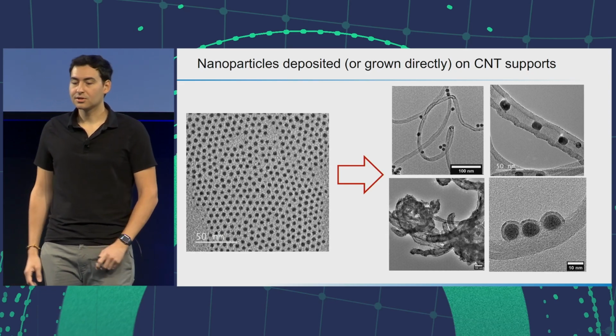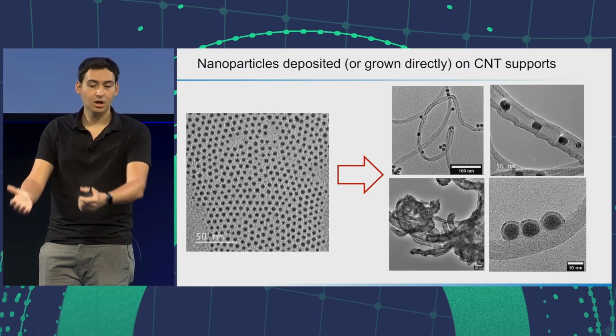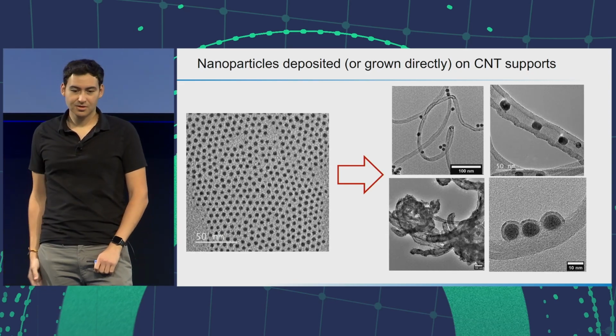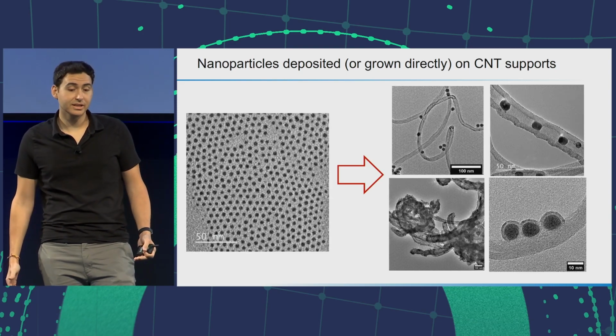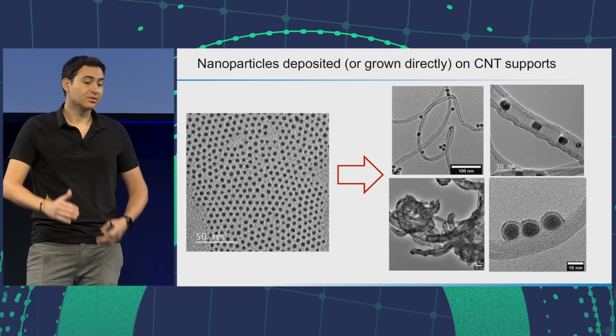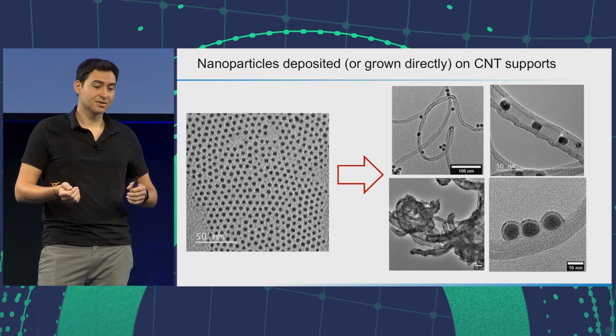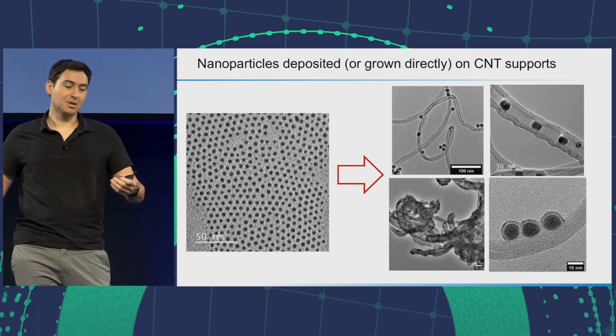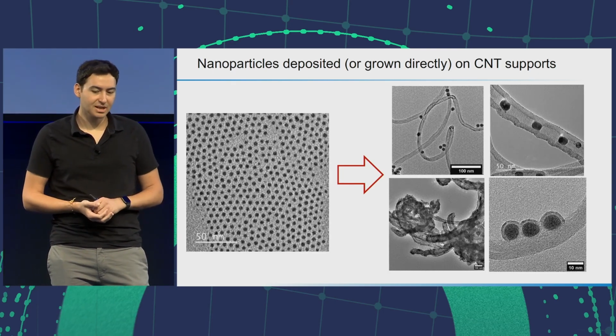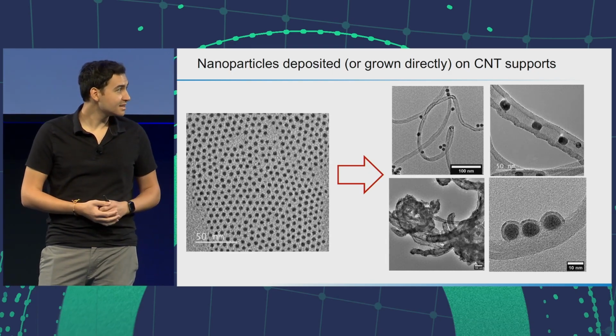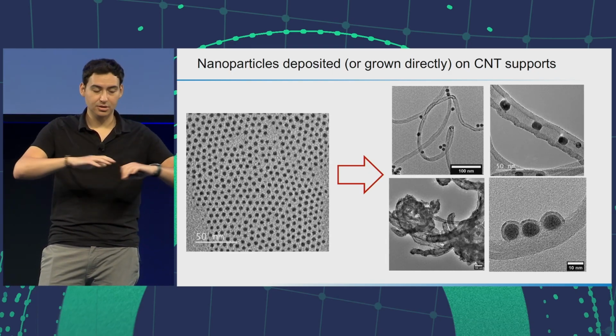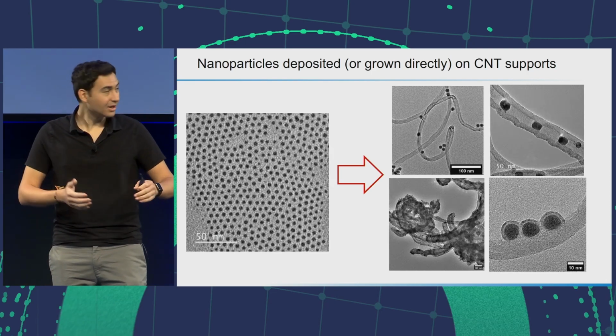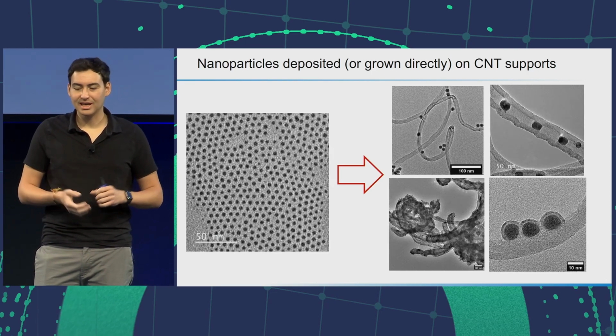And we take these particles and then combine them with our support, so carbon nanotubes. We have a million of these pictures, but I just wanted to give you a few that are representative of what we can do. We have different quality nanotubes, so we could put the particles on top of the nanotubes. We could put them inside and clog up the nanotubes. We can put a high weight loading density on the nanotubes, very small particles, in a very busy environment you could see there, where sintering can be a risk.